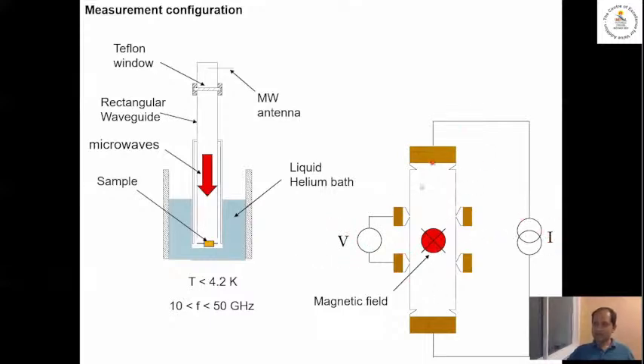So we have a sample like this. It sits at the bottom of a cryostat, and we have wires coming out from the sample. And then there's also a waveguide here. And then we connect a microwave oscillator, excite microwaves, and the microwaves go down and impinge on the sample that's sitting at the bottom. Now, there's also a magnet over here, which is not shown, a solenoid, which produces a magnetic field in this direction, right?